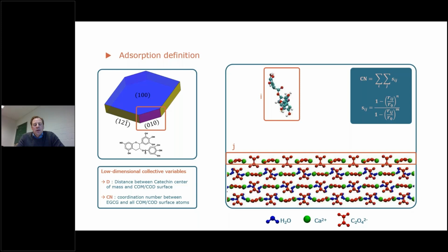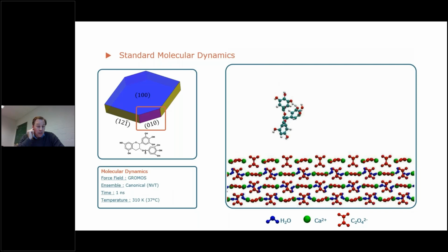And this is what we obtain if we do a molecular dynamics. Be careful, here it is with force fields, so it's not first principles. And the white above the surface is in fact filled with water molecules. So you don't see them, but they are there. What happens is that we can look at this movie during hours and hours, and maybe it will never adsorb on the surface, because this is what we call a rare event. A rare event on the time scales we use.